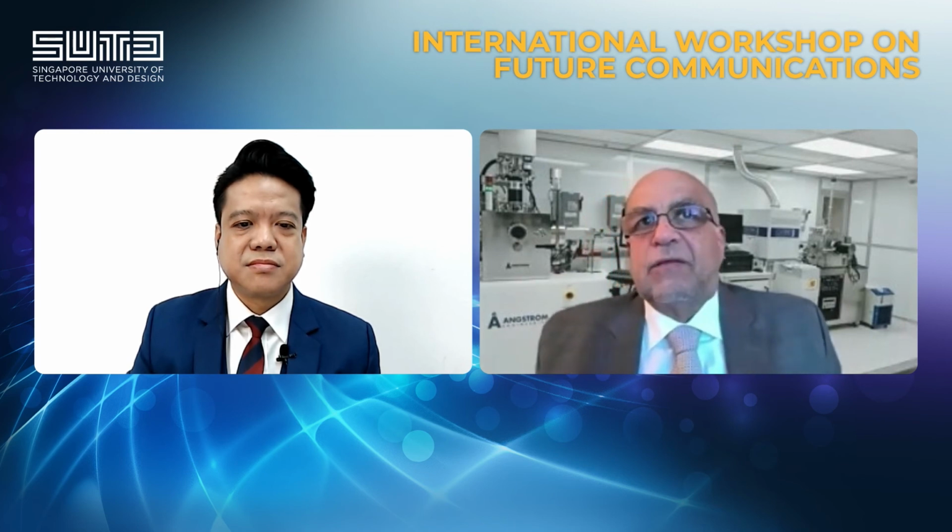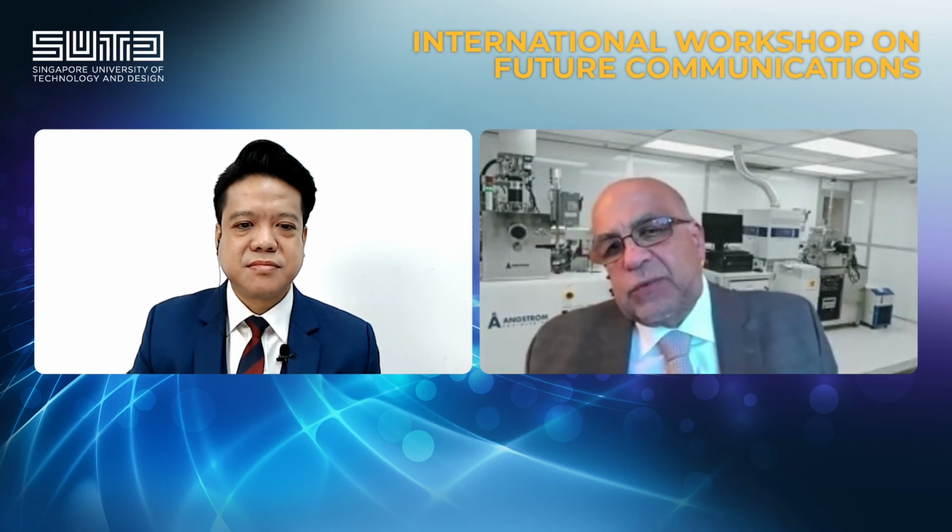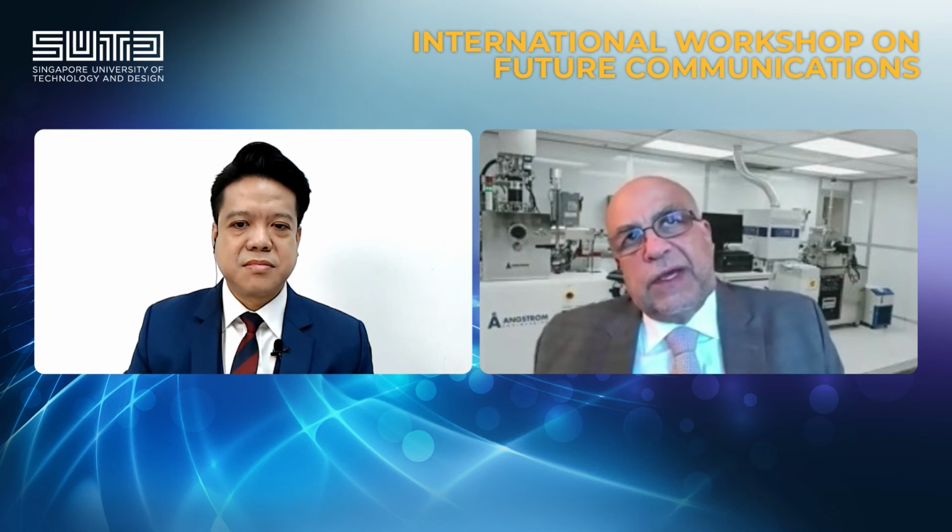Now, why does this happen in the off state? Somehow the capacitance is so low that there is tremendous voltage on it, so the material switches back inside and goes to the on state. So you need some work in that area to improve it further. But what we hear from some people is that if you can get a PCM switch to work for 4 watts or so, that will be great. So it's getting there. As I mentioned, the technology started just a few years ago for RF applications, and still more research needs to be done.